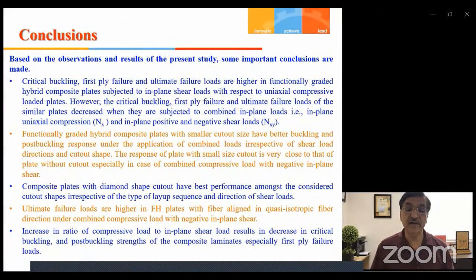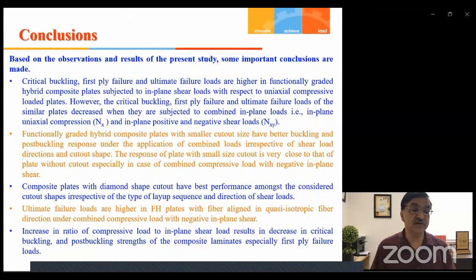Finally, the critical buckling, first ply failure and ultimate failure loads are higher in a functionally graded hybrid composite plate subject to in-plane shear load with respect to a uniaxial compression loaded plate. The critical buckling, first ply failure and ultimate failure loads of the similar plates decrease when they are subject to combined in-plane load, that is, in-plane uniaxial compression and in-plane shear linear load.